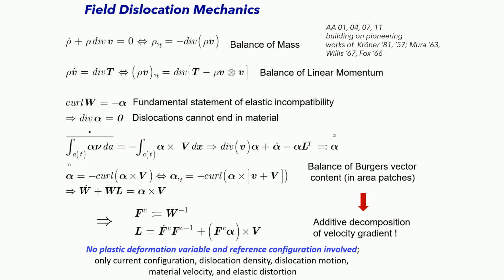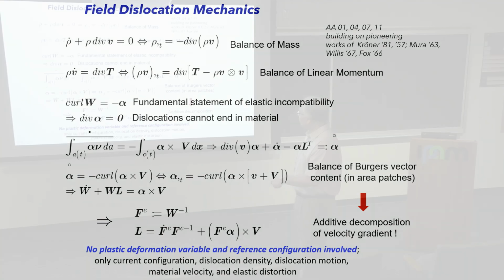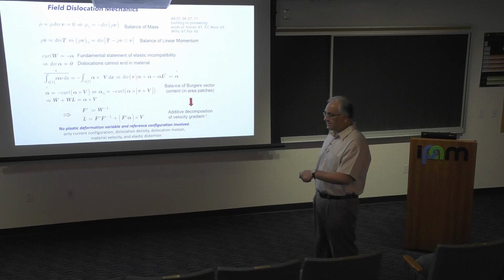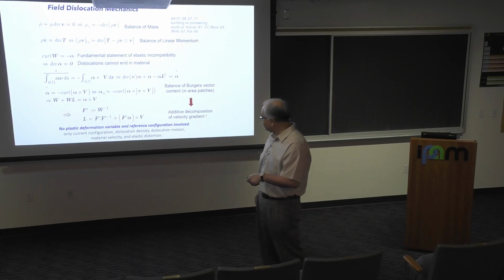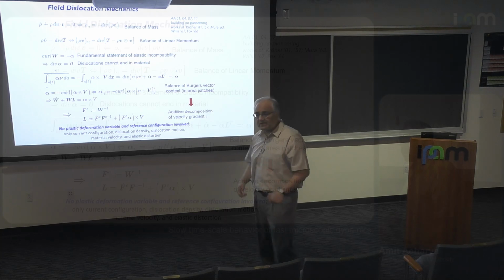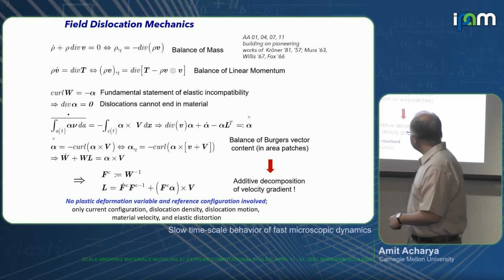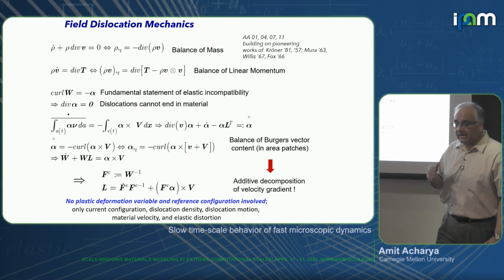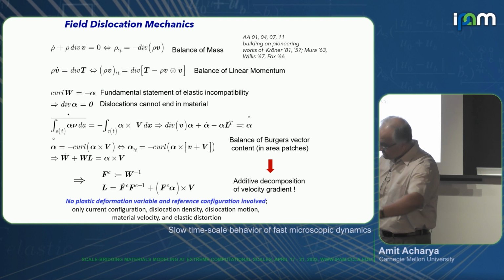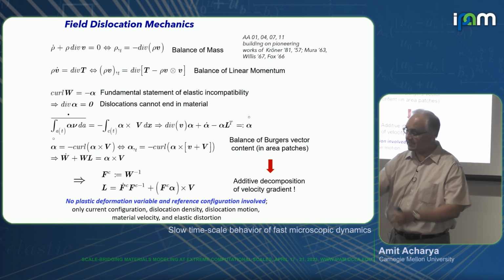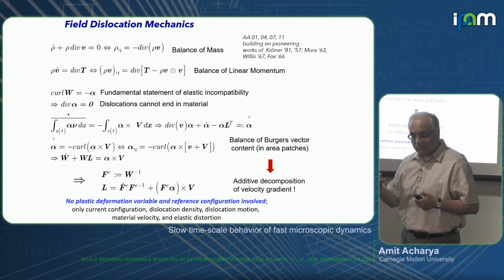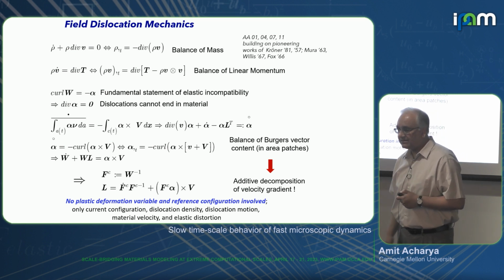The spatial time derivative is curl of alpha cross. This is the material velocity, and this is the relative velocity of dislocations with respect to the material. So this looks, for those of you who've stared at the vorticity equation, very much like vorticity, except this is 3 by 3, a matrix. And dislocations move relative to the material. So this is this capital V. If capital V was 0, then dislocations can move along just like vortices, but there is no dissipation then. That's the elastic theory of dislocation.